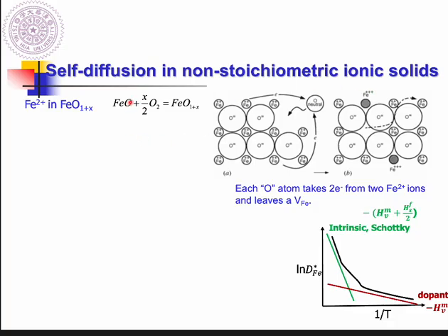Based on the questions, we have a matrix that is FeO with two positive charge of the iron. But the non-stoichiometry effect means that inside my material, not only do I have iron with two positive charge, I also have some iron with three positive charge. Not all the iron has the same positive charge. That's what you will call the non-stoichiometry effect.